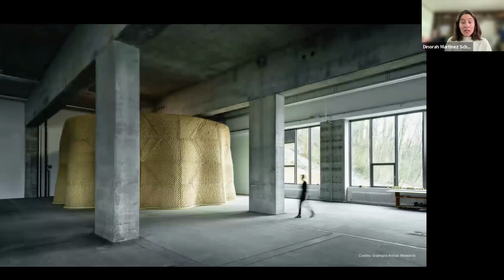It's called Clay Rotunda, and this is the final result that they did. You can see how these sections, if you see my cursor, or the arrow, you can see how the different stages of fabrication started to be placed in the whole wall. The whole wall was not printed as a monolithic element, it was printed in different discrete elements as they were needed. And we also use the force of the machine to avoid using concrete or wood structures inside the wall, and the wall didn't have any structure. The structure is totally given by the earth.